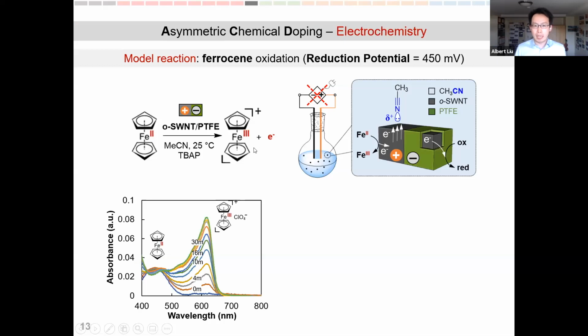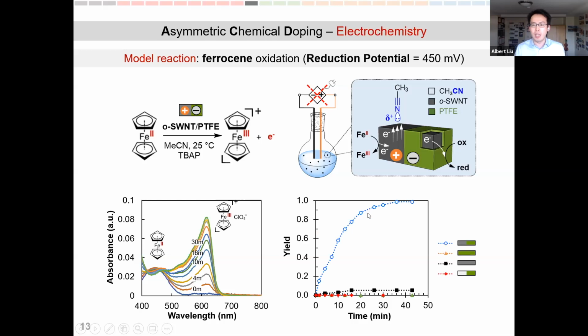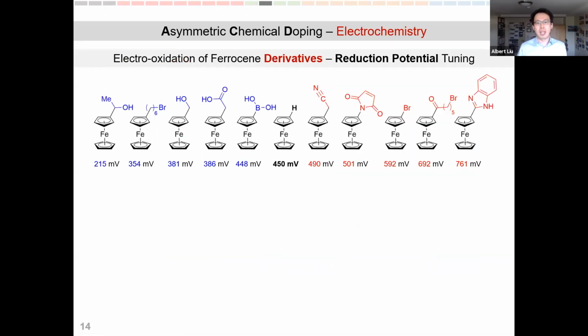So the experiment was super easy. You basically put these particles into a beaker of acetonitrile that has ferrocene in it, and we can just observe the color change as ferrocene is being electro-oxidized into ferrocenium. We can observe the reactivity using UV spectroscopy and measure quantitative yield for Janus particles that we fabricate using the aforementioned method. The nice thing about an electrochemical reaction is that its reactivity is typically governed by reduction potentials. And with ferrocene derivatives, we get our hands on a wide array of chemical substrates that have different reduction potentials compared to the parent ferrocene molecule.